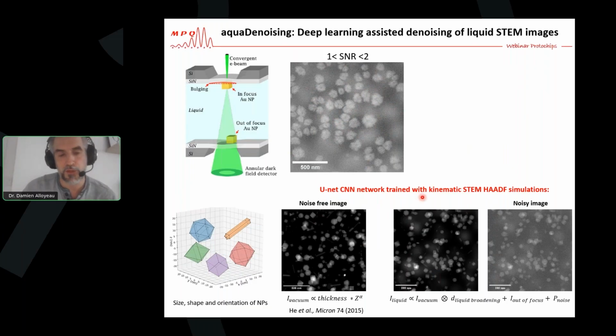To train our UNet networks, we use kinematic STEM HAADF simulations, which allow us to take into account the variety. The key is to take into account the variety of size, shape, and orientation of your nanostructure within the liquid cell. So that's what we did. We put in a lot of different types of shapes and sizes of nanoparticles. And then you calculate the noise-free image that consists only of the thickness of the nanoparticles at a given point, multiplied by the Z atomic number. So it's a very simple, atomistic, kinematic simulation.